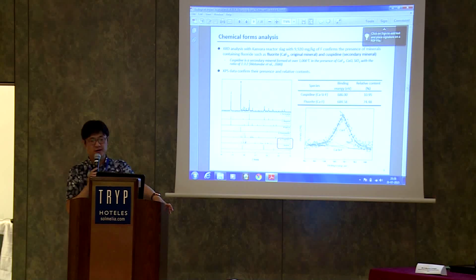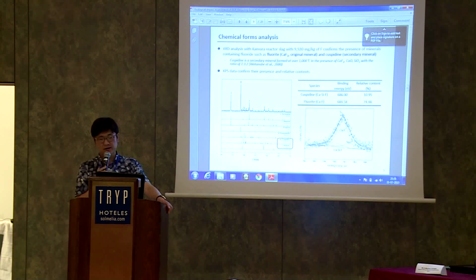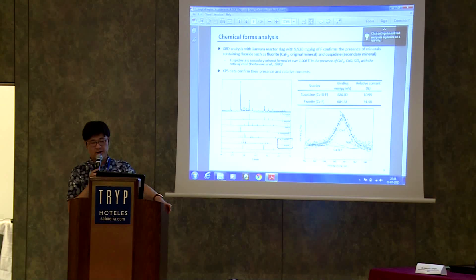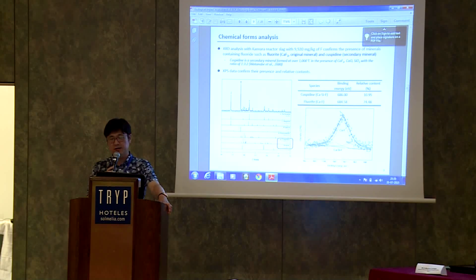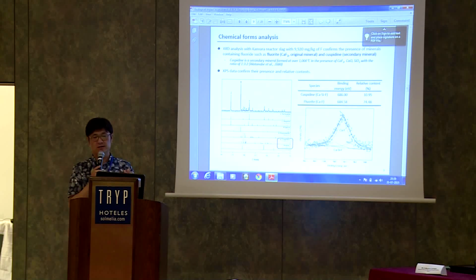I also performed some analysis like XRD and XPS to confirm such chemical forms in the slag. The XRD graph shows the presence of cuspidine and fluorite in the slag. Fluorite is an original mineral, calcium fluoride, and cuspidine is a secondary mineral produced from the fluorite. And XPS data also confirms the presence of cuspidine and fluorite, yielding binding energies corresponding to the two minerals.